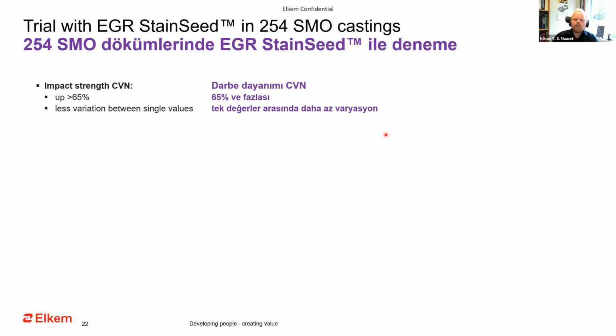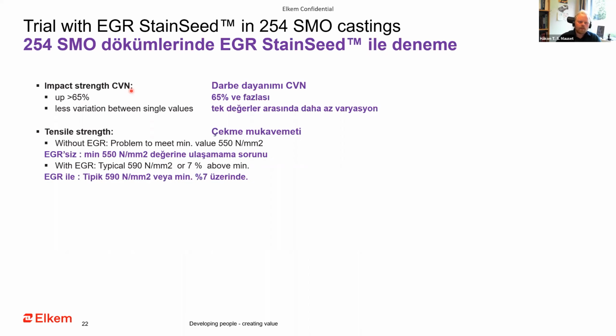Then the next trial was 254 SMO castings at a foundry. And they had problems achieving the mechanical properties for these castings. Both impact strength and also the tensile strength was a problem. And they had problems with the surface. They had to do a lot of weld repair on these castings. I think it was valve bodies.